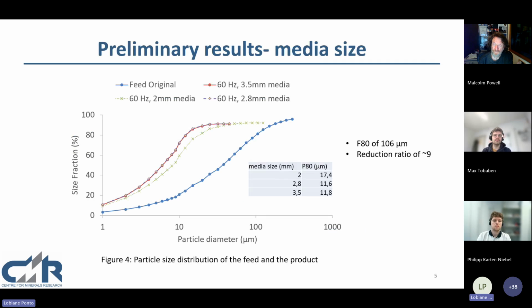And so these are the results that I have from grinding the tailings. It's just the preliminary results, where it shows that I have a reduction ratio of about 9 for using 3.5 millimeter ceramic media. And it shows that the media of size 3.5 and 2.8 millimeter show similar product sizes.